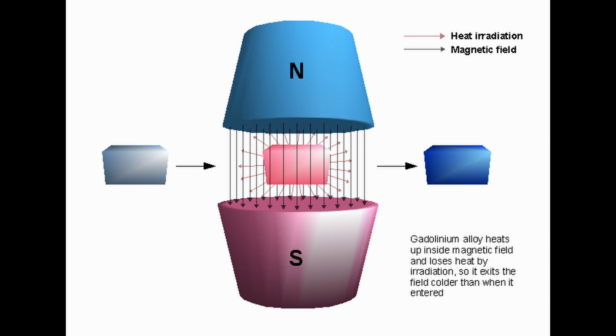So predictable and well-behaved is a good thing. But didn't you say the Gd5Si2Ge2, with its giant magnetocaloric effect, happened below room temperature? Does that mean that maybe these first-order transitions are better in terms of how strong the effect is? That's a great observation. You're absolutely right. While gadolinium is reliable, the materials with this giant magnetocaloric effect, often tied to first-order transitions, can really pack a punch. They give you much larger temperature changes for the same magnetic field change. Gd5Si2Ge2 is a huge discovery, but the problem was that its transition temperature was about 270 Kelvin, which is too cold for a typical fridge.